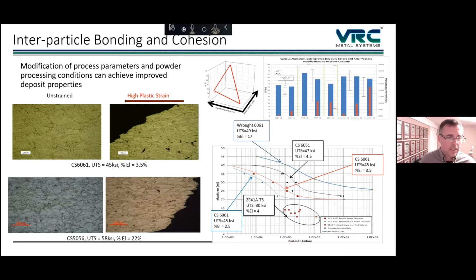So in the top here, you see something that has 3.5% elongation, and you can actually see the defects opening up in the high strain region. You can see pores opening up. In the bottom images, it's a different alloy, and we're able to get up to very high elongation. And in this case, you see very few interparticle defects and significant amounts of strain in the individual particles themselves.